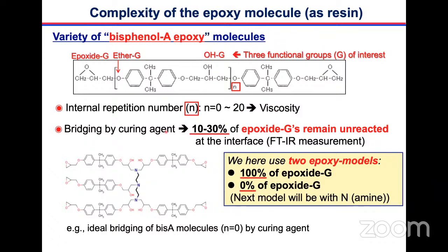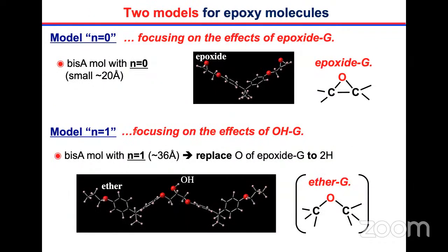Then we need a curing agent to make a bridging of these epoxy molecules, something like this. We have the curing agent here, and five epoxy molecules bridged together. Then some epoxy groups still remain. According to the experiment, 10% or 30% of these groups remain unreacted at the interfaces. Because of this, we use two extreme models for the hybrid simulation. One model is that 100% of the groups still remain. The other model is that 0% of the groups remain. So this is the model we use.